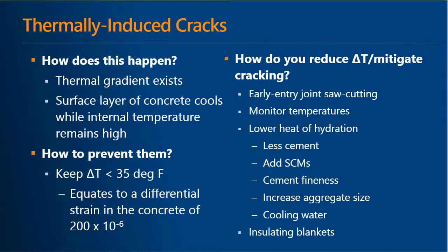And so one way to reduce or mitigate the potential for thermally induced cracking is to, say, use early entry joint saw cutting to try to relieve some of that pressure. Use insulating blankets and try to also lower the heat of hydration of your concrete.